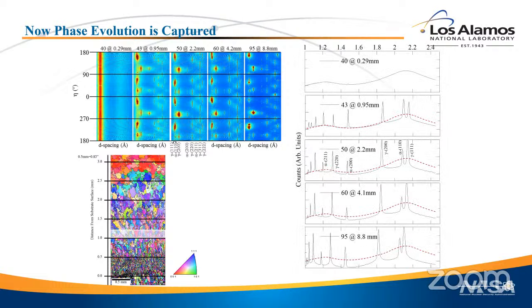If you take those diffraction patterns on the left and integrate them vertically over that angle eta, you get what we're used to seeing as diffraction. On the top is again the liquid. Those broad peaks are the liquid scattering. If you go a millimeter away from the melt pool, you can now see, and the red dotted line is just a copy of the liquid scattering translated downward.